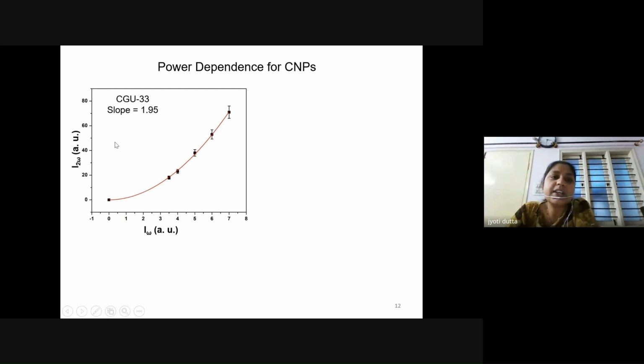So we have measured the power dependence plot for these carbonaceous nanoparticles to ensure whether it is a multiphoton fluorescence, and if it is a multiphoton, whether it is two photon or three photon fluorescence. So for the power dependence plot, we observed that the slope of the power dependence plot is 1.95, which ensures that the multiple photon fluorescence that we are observing for these carbonaceous nanoparticles is actually a two photon fluorescence.